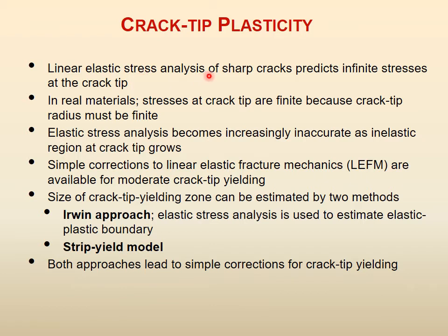Linear elastic stress analysis of sharp cracks predicts infinite stresses at the crack tip, right? If the crack is very sharp, the radius of curvature is 0, so therefore infinite stresses. In real materials, stresses at crack tip are finite because the crack tip radius must be finite. Elastic stress analysis becomes increasingly inaccurate as inelastic region at the crack tip grows, right?